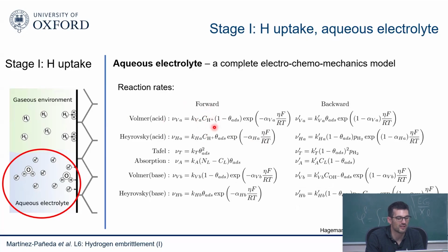This is going to be given by the electrochemical calculation. The reaction rate comes from an experiment; this is a material property. Absorption is given by the occupancy of the surface, from the calculations. And then all of this, overpotential, temperature, gas constant, everything is known. The overpotential is given by the electrochemical simulation, the same as the pH. It changes in space. And then you have basically a reaction rate. So everything is known. This is the way to go.